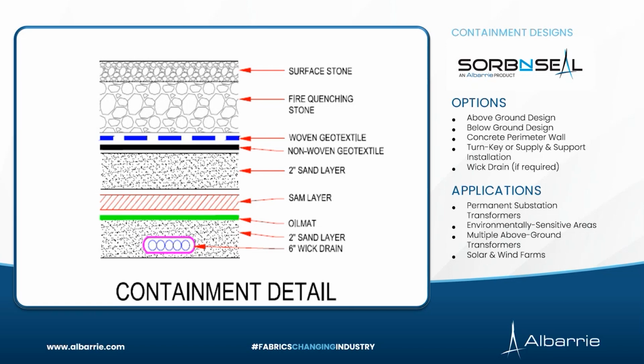Now, this is a very popular design for all kinds of substations, in retrofit applications where you're trying to add containment afterwards so that the substation can meet today's environmental standards. In new installations, obviously for larger equipment, it's more cost effective than, say, a traditional concrete containment. For smaller equipment, it is still a pretty good option. The savings between large and small equipment might be a little smaller when you compare it with concrete. But if you look at the life cycle value of this system compared to a traditional concrete pit, you'll find that in the long run, this is a much better value.